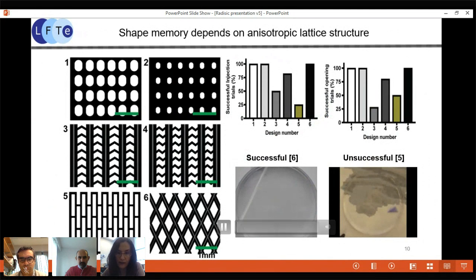The molds afforded different lattice shapes to the scaffold, and you can see that he graded the percent of successful injection trials, as you can see in these videos, and the percent of successful opening. So the video is illustrating what it looks like when the scaffold successfully opens and when it unsuccessfully opens. And from these, we found that, for example, design 6, as well as designs 1 and 2, exhibited 100% success in both of these criteria. But we decided to focus on scaffold design number 6 because these straight lines and the channel that was patterned on top of the straight scaffold lattice enabled us to control cell orientation.